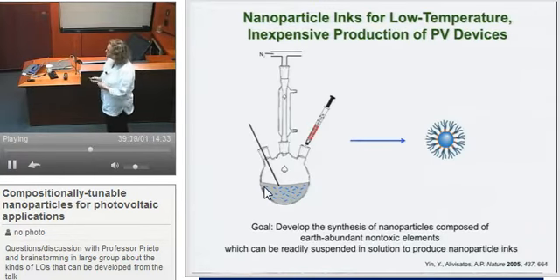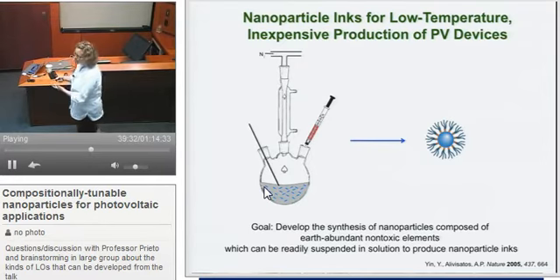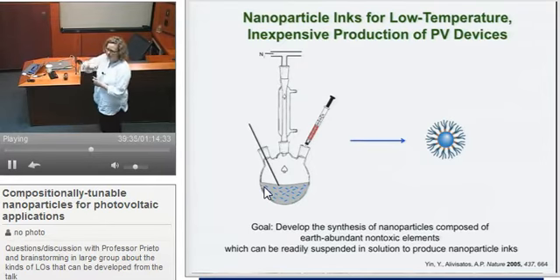And the key here is that at the end, you end up with this nanoparticle where the core is the inorganic piece, the solid state piece, and ideally that's where you can control the electronic properties of your material. The surface is coated with these organic molecules. Again, to highlight that I'm not an organic chemist, this is a cartoon of a very common surfactant called trioctylphosphine oxide, where you have a phosphorus double bonded oxygen that's very typical in terms of a polar head group, and then you have these long alkyl chains that are very hydrophobic.